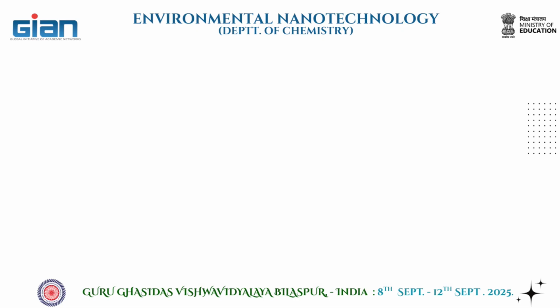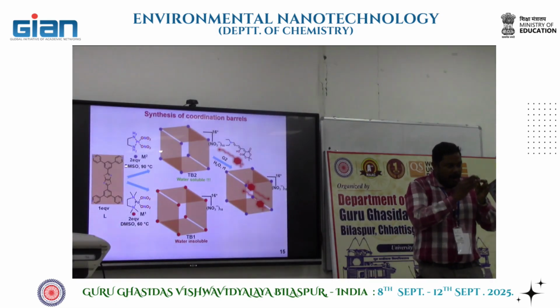For example, this one. This acceptor is designed in such a way that it can accommodate a 90-degree angle, square planar metal. So one side is blocked, another side is open. So it has a 90-degree angle, and this is a stable molecule which is planar, so in plane it can coordinate. If it can hold the 90-degree angle and these two can bind, then there is no strain. Following this design principle, coordination architectures depend on the donor-acceptor binding angle.